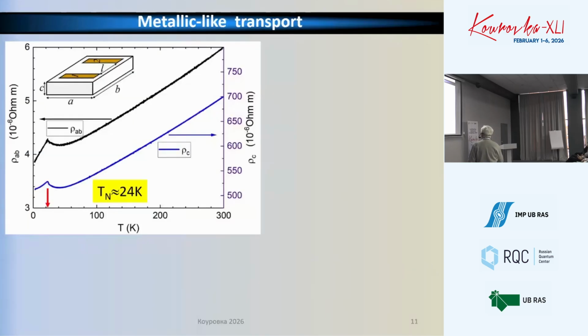In zero field, the resistivity temperature dependence immediately confirmed that we deal with a normal metal. You see that there is a huge anisotropy, about 2 orders of magnitude, between the resistivity in plane and perpendicular to the plane. And it decreases down to the lowest temperature, with the exception of this kink. The kink corresponds to the magnetic ordering temperature, which I will explain further. This is the Néel temperature. And the rise here before the kink is just normal textbook behavior associated with antiferromagnetic fluctuations. This I show just to confirm that we deal with a normal metal, and no signatures of topologically non-trivial states can be found either in band structure or transport properties. Nothing unusual.